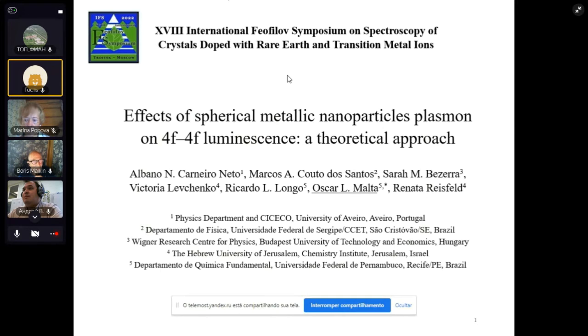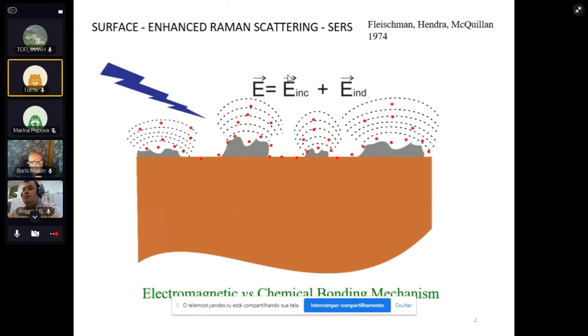As you may see the title of my talk, let me just start with a small history, only two slides. The first one is that probably most of you remember the so-called surface enhanced Raman scattering, or SERS phenomenon, which was discovered in 1974 by these two gentlemen. The idea is that you put on a surface of a substrate a metallic island in the nanoscale or microscale. And when you put molecules around it and you excite and you look for Raman scattering of these molecules, they have identified an enhancement factor of the Raman scattering cross section by about 1 million. So this is an extraordinary observation.